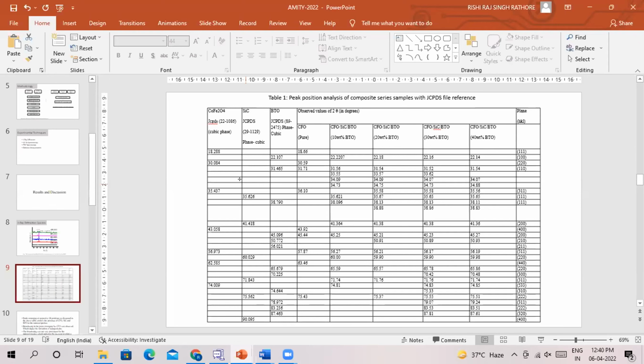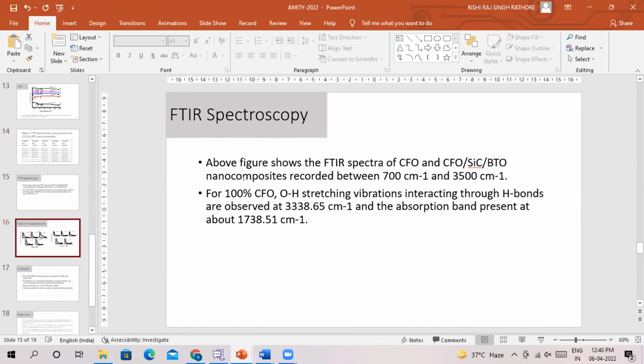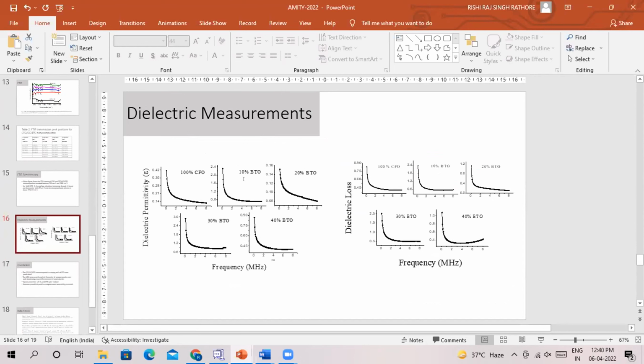Another one with the dielectric results. Yes, sir. What is the reason for possible changes like this with the formation of composites? I mean, sir, like I mentioned in the presentation also, the change is not uniform. But the possible reason we figured could be that the number of compounds we are using is 3. It's not a binary composite, but it is a ternary nanocomposite. And such results have been achieved in other literature also, where ternary nanocomposites are found to give dominating roles by particular compounds sometimes and the other compounds at other times. So that was the possible explanation we could find for this type of irregularity in the data.